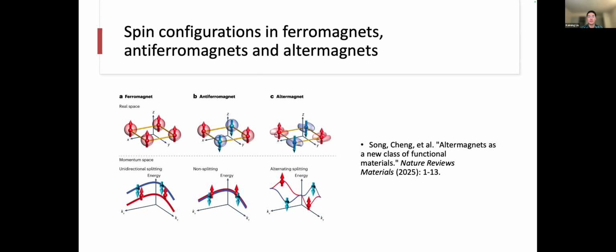I will compare the concept with ferromagnet and antiferromagnet. In ferromagnet, spins are parallel in real space, so it has a net magnetic moment. In momentum space, the energy band shows unidirectional splitting. And in traditional antiferromagnet, spins are antiparallel, so the magnetic moment is cancelled in real space, which means it has no net magnetic moment. So in momentum space, the energy band doesn't have spin splitting.